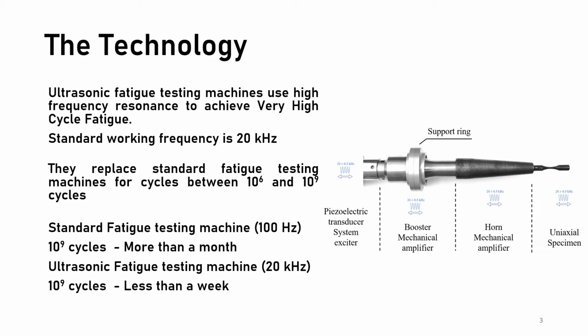Now the technology behind ultrasonic fatigue testing machines. These machines use resonance as a way to induce high-frequency fatigue. This is to study the very high cycle fatigue regime between 10 to the power 6 and 10 to the power 9 cycles. If we compare this to the standard fatigue methods, to reach 10 to the power 9 cycles can easily take more than 1 month, while in ultrasonic fatigue machines, we can easily take less than a week.